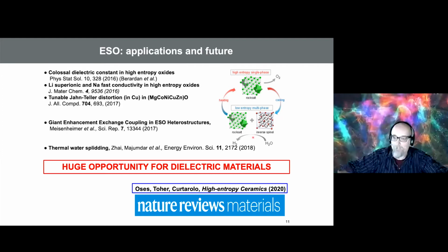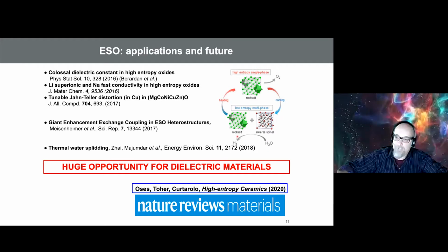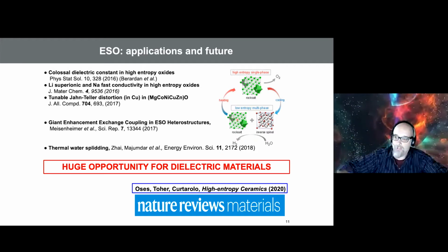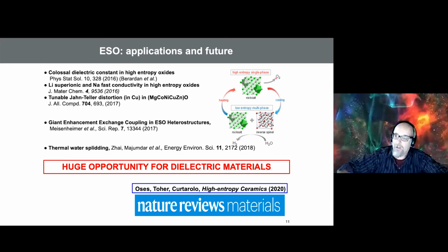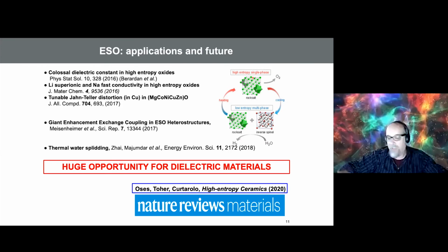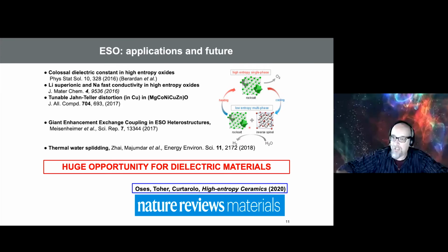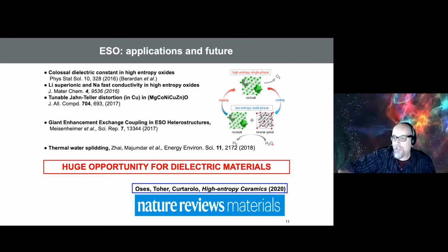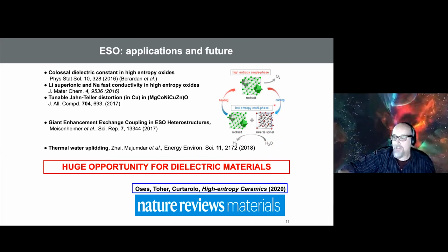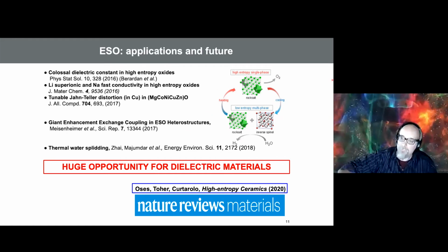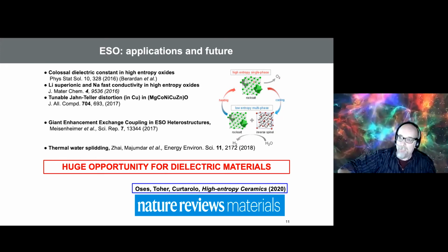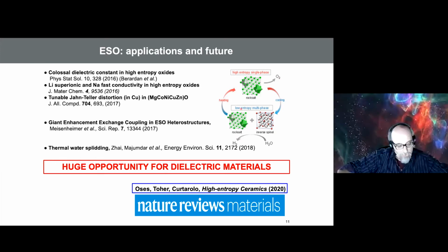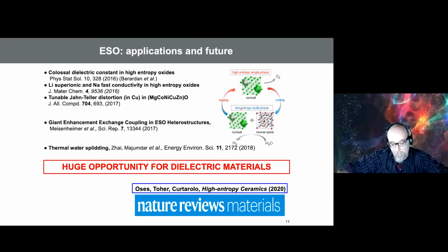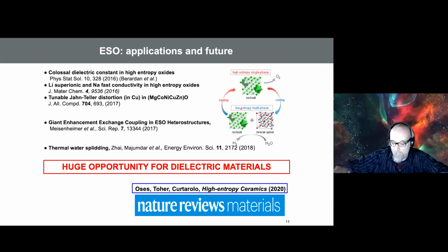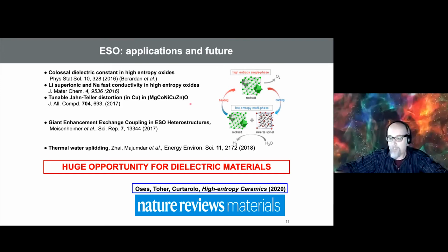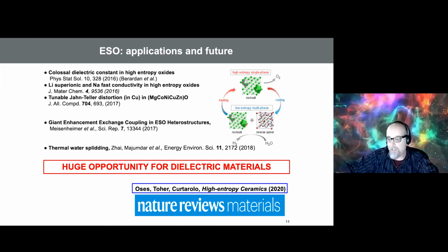So pretty much you are able to chemically split water, right? Because at low temperature water splits and the hydrogen is released while the oxygen remains inside, but at high temperature the oxygen goes out because the rock salt cannot keep oxygen inside. And then pretty much you transfer the heat of the decomposition of water through this heat pump going up and down in temperature through these materials, right? So the idea is that if you're interested in catalysis, if you are able to reduce this temperature with better oxides to temperatures like generation 4 nuclear generators, we would be able to generate a lot of free hydrogen and oxygen, right?